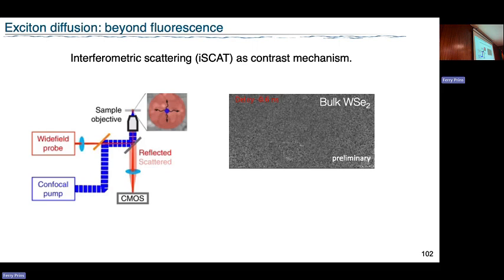No, you excite with a pump pulse. What you're doing is you're ever so slightly depleting your ground state, so you're changing the absorptivity of your material. Change the absorptivity, and Kramers-Kronig tells you that you're changing the refractive index of the material.